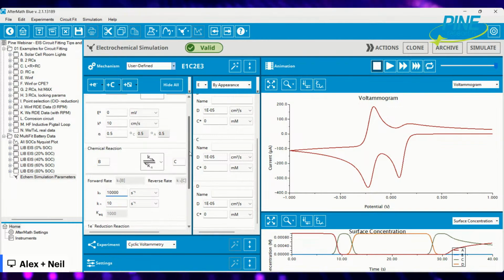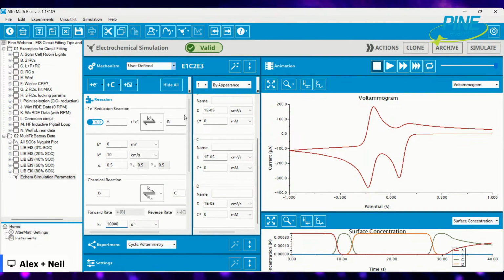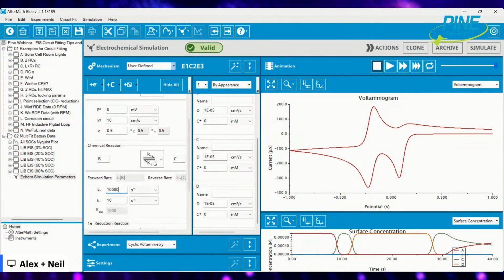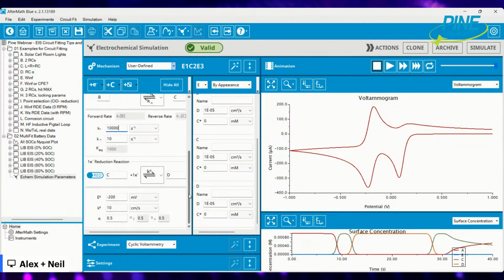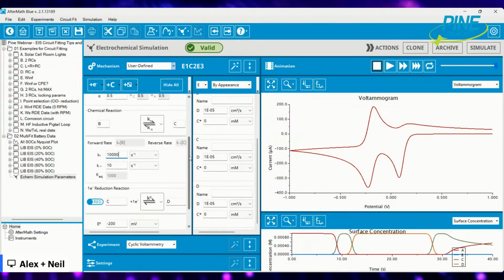The reason for this is that I just made up an arbitrary reaction mechanism where A goes to B, an electrochemical reaction. Then I have this chemical step where B can go to C. And then I have another reaction where C goes to D. It's like 3 reactions, right? The only thing keeping me from getting this last peak is that the chemical reaction I have is driving extremely fast. All of the B is going to C. So I don't get this last oxidation step because once the B shows up from this oxidation, it all is chemically reacted. And so I don't get my last peak. Those are just 2 answers.